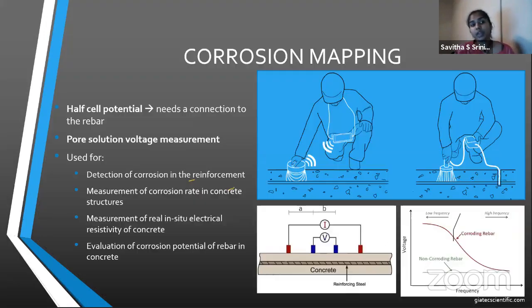The other place where NDT is gaining a lot of traction is in corrosion mapping. So earlier we had to use the half cell potential measurement, which needs connection to the rebar. So you have to drill a hole in your concrete specimen and then attach a wire to the rebar itself and then take your measurements. But with the new resistivity meters, you don't need to do that. Essentially, it just measures the voltage of your pore solution or the surface pore solution to calculate if the rebar is corroding.